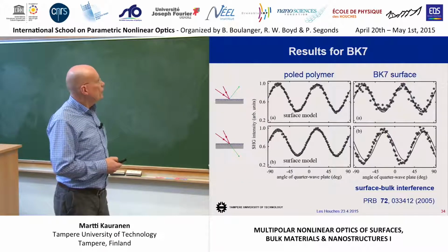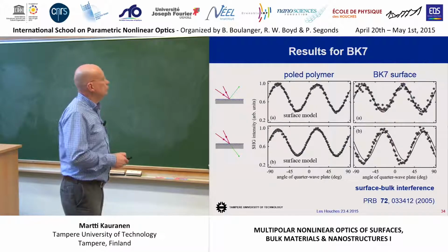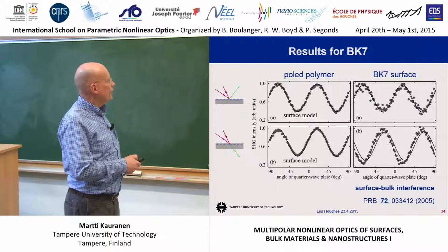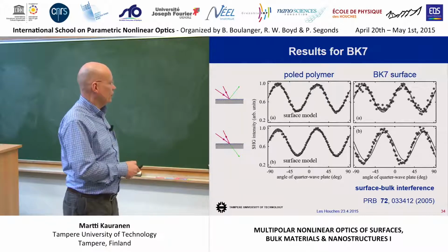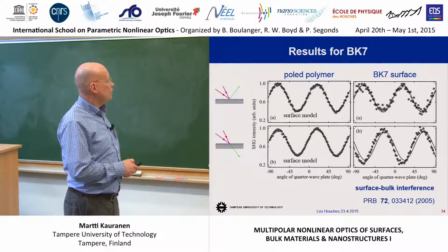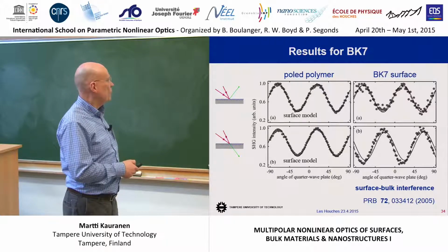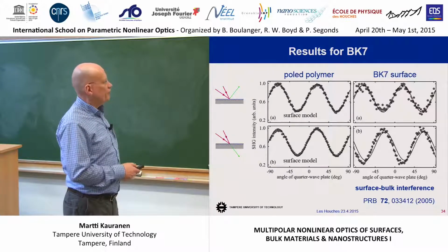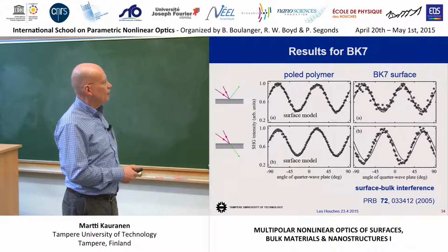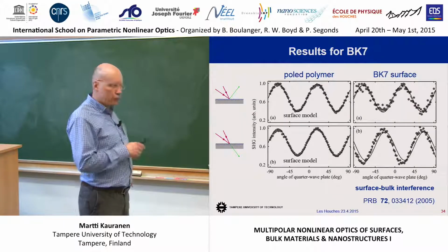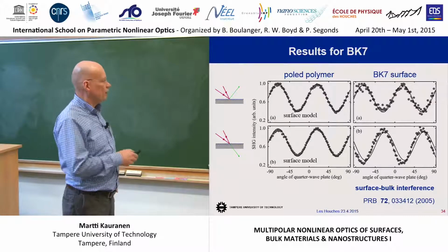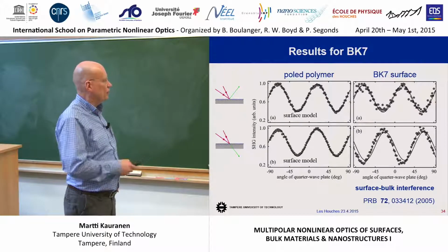And this is how it works out. This is the poled polymer sample, and here is a fit to the data using the surface model only for the reflected and transmitted signal. And you see here that both cases fit almost perfectly to the surface model. For the glass surface, the reflected signal, there's a pretty good fit, but there's another fit that includes both surface and bulk response, and it's slightly better. We are going to have a closer look at that in a second.